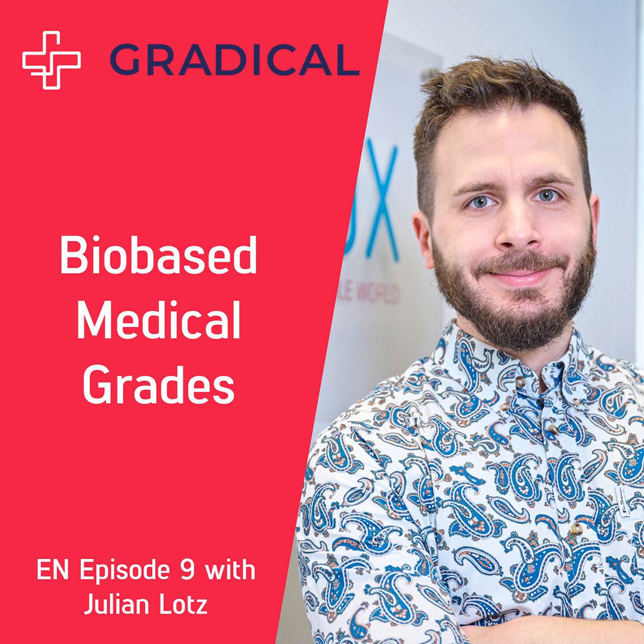But for PLA, you usually need higher temperatures and/or high humidity levels. So if you stay at 80% or lower relative humidity, and below like 50 degrees Celsius for long-term conditions, then you don't see much degradation in the usual 3 to 5 years of shelf life. So that is quite fine, and we have samples here in accelerated aging, currently at an equivalent of like 7 years or something, and you don't see much difference to the new material.